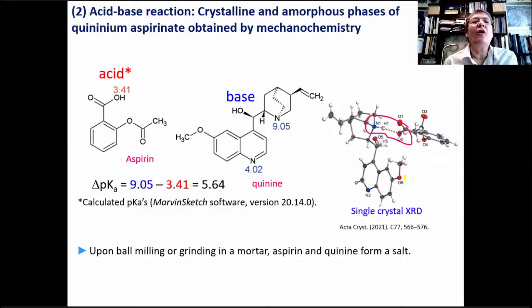So the second type of reaction to study is an acid-base reaction, the formation of a salt between quinine and aspirin. In this case, using the delta pKa rule, we can calculate those values with software, or we can obtain them experimentally. If delta pKa is more than 3, the material should form a salt, and that is observed experimentally, in which a proton from aspirin is transferred to the most basic site of quinine, forming this salt, and the structure is known by single crystal X-ray diffraction.